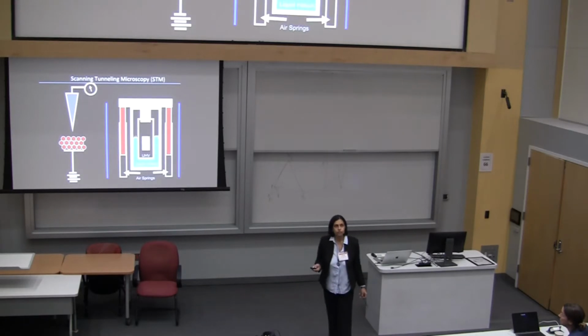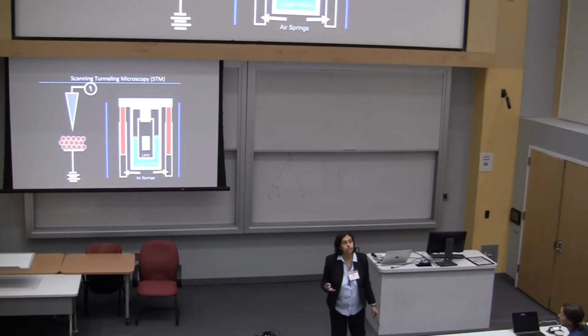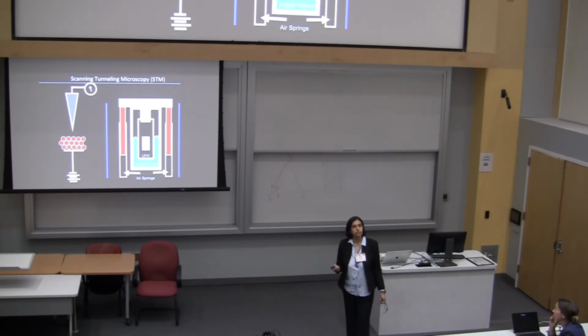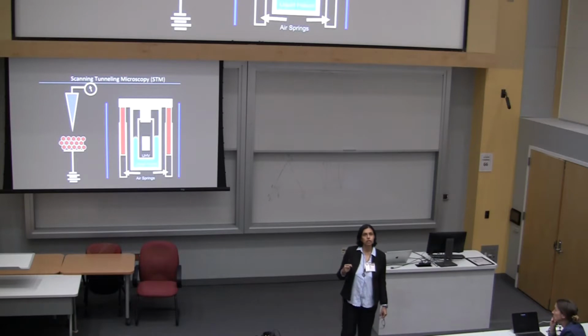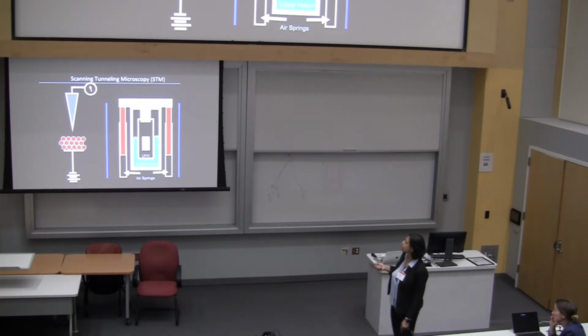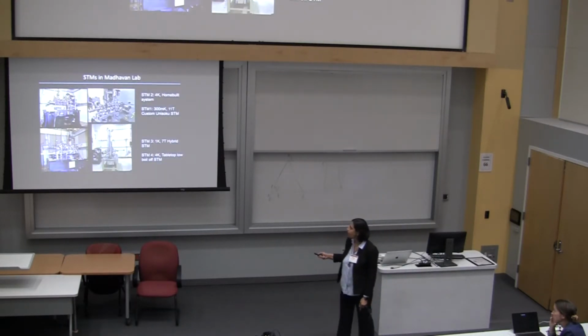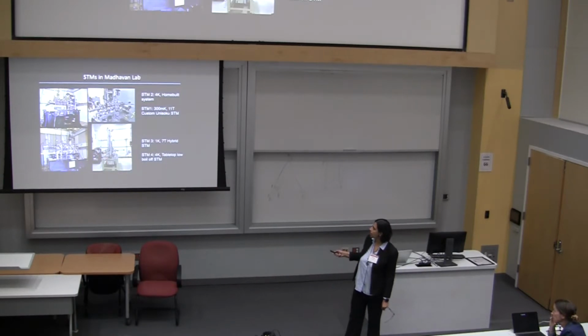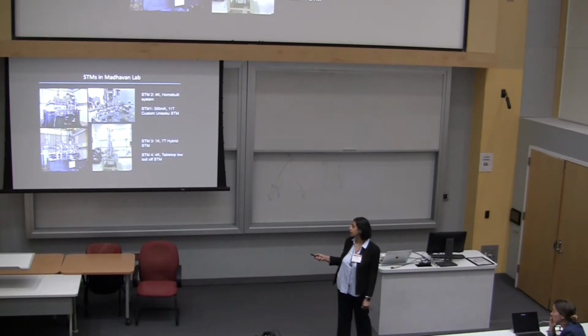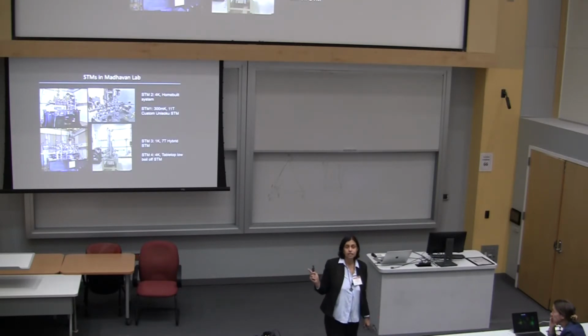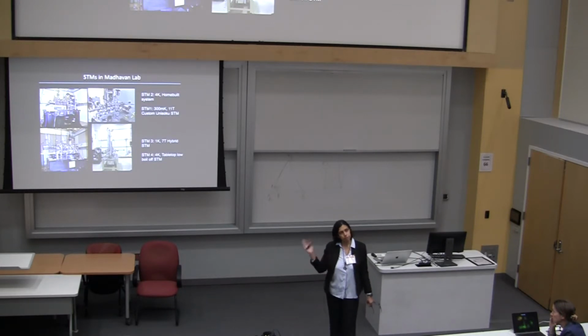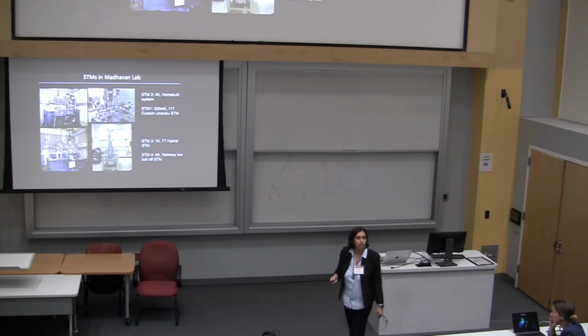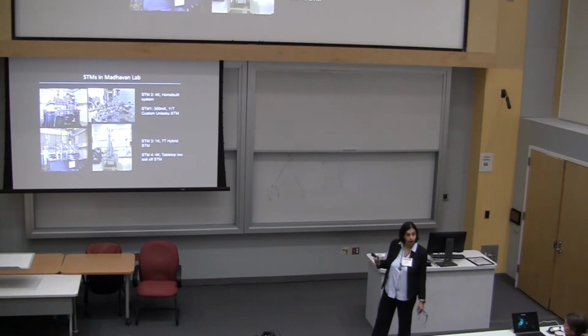Most STMs that we use, in fact all of them, are used at low temperatures. This is really important to us because low temperature allows us to get high energy resolution. It also allows us to have clean surfaces for large periods of time, for months at a time, so we can sometimes make measurements on the same sample for 2 or 3 months. We have 4 STMs, and one thing I want to point out is this commercial system, funded by the Moore Foundation. When we grow our films, we can put them into this tabletop STM, quickly look at the film and take it out all within one day. So it really gives us the ability to screen our samples very fast.